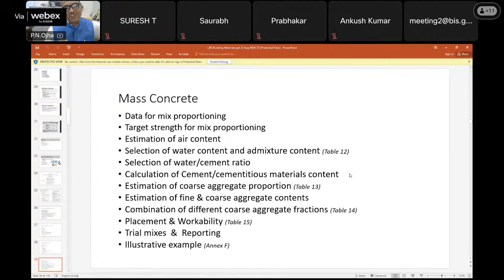One more restriction is there should be sufficient mortar content when 80 mm plus or 150 mm plus maximum size aggregate is designed. And especially these types of concrete are used in dam construction. Mass concrete is also used in high thickness foundations, like if a foundation of a 100-story building has 2-meter or 1.5-meter thickness, that can be called mass concrete, and that becomes tricky because of the temperature generation in the core of the concrete. And how to control the temperature, all these tricks and arts, all these standards are available. One will have to study mass concrete in detail.